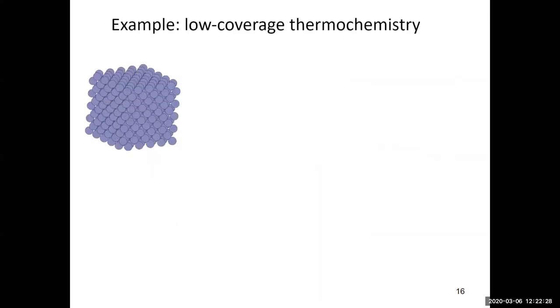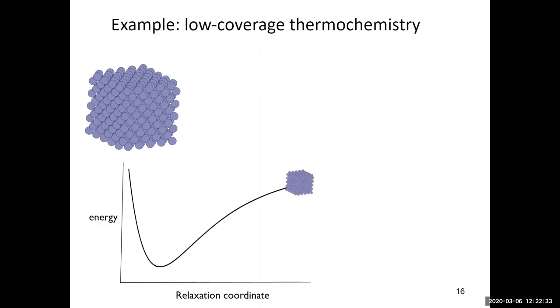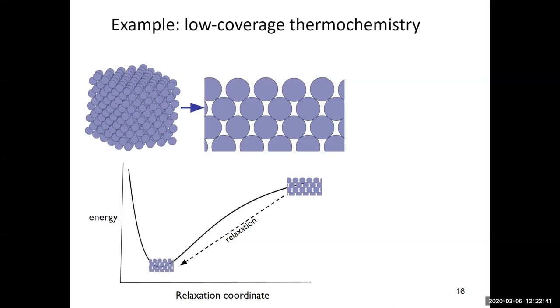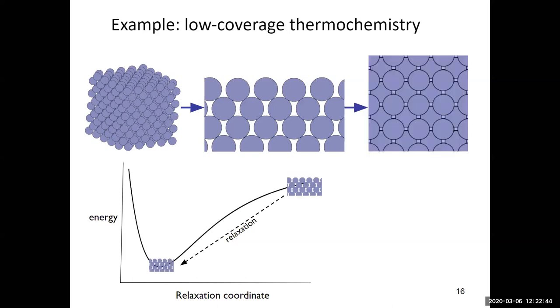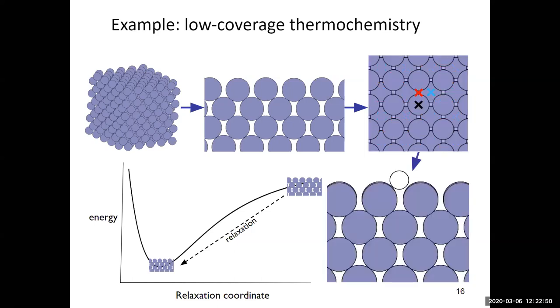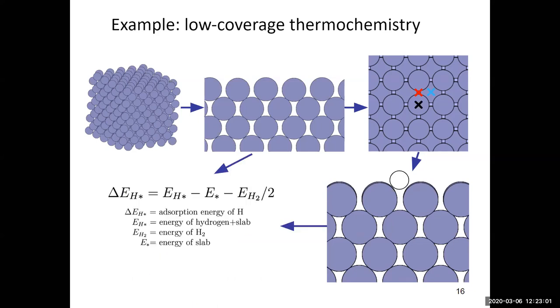Okay, so surface chemistry involves a lot of different steps, just like bulk material properties. We need to do a lattice relaxation if our calculation settings are a little bit different from the Materials Project's to get the lattice constant correct. We then need to cut the surface and do a relaxation. We need to analyze the surface and say, where can I put an adsorbate? So in this case, there's three unique sites. And then we need to put the adsorbate down and we need to do a final relaxation. And so there's multiple calculations that all have to get orchestrated together. The adsorption energy that we calculate at the very end is this structure minus the blank one, minus wherever the hydrogen is coming from. So relatively straightforward.